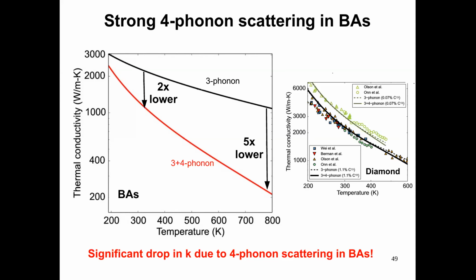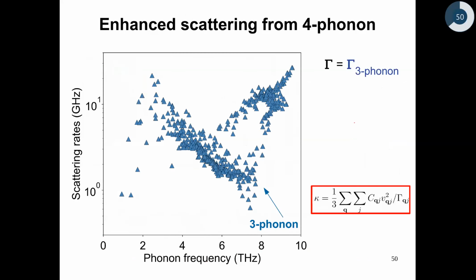When we did the calculation for diamond, including 4 phonon scattering, we hardly noticed any change in the calculated thermal conductivity. More importantly, we still got excellent agreement with the experiment over the broad temperature range. Okay, so now we have an algorithm, or a first principles code, with which we can calculate the properties of phonons very accurately. So with this code, we can actually go beyond just calculating thermal conductivity, right? We can actually look at the microscopic origin of such a large reduction in thermal conductivity of boron arsenide.